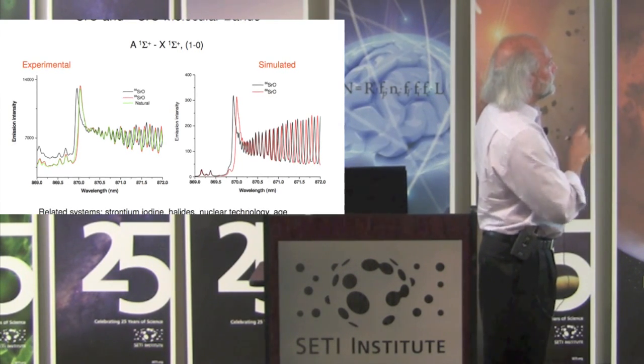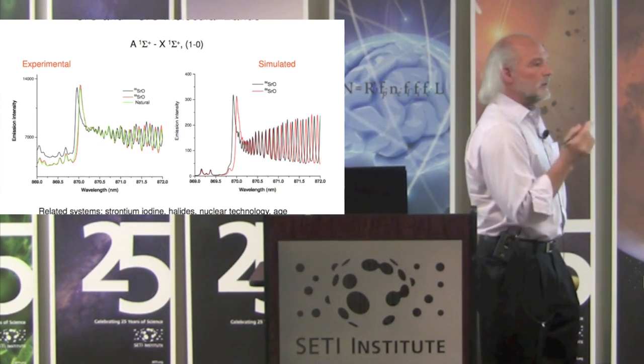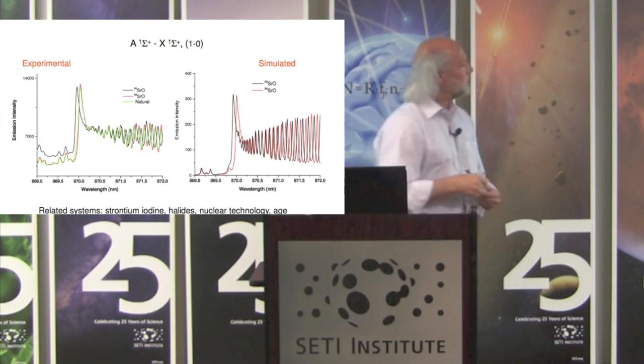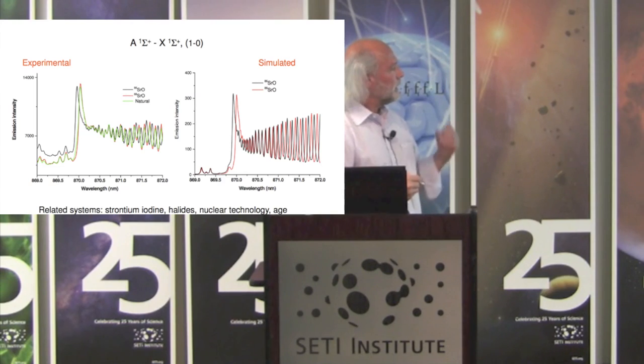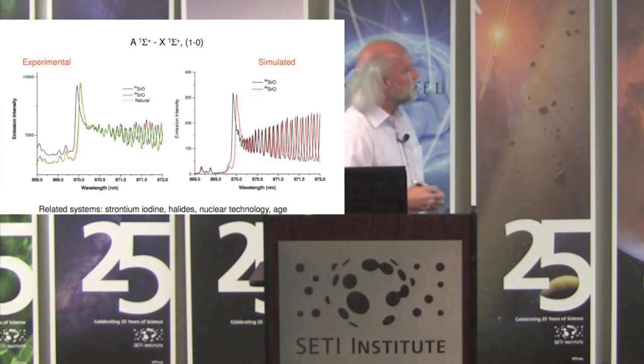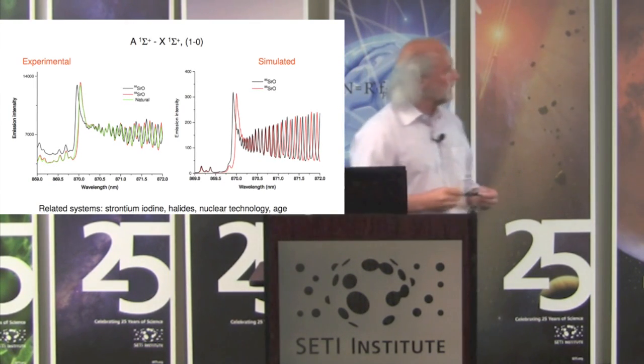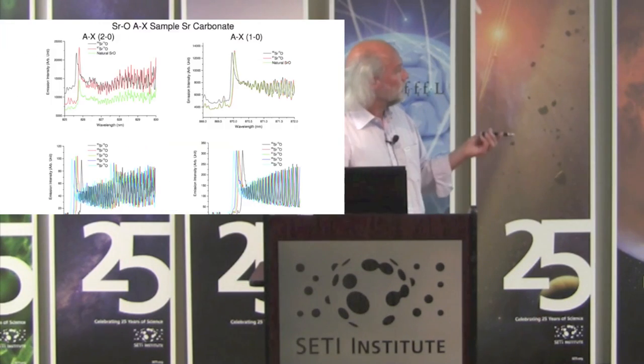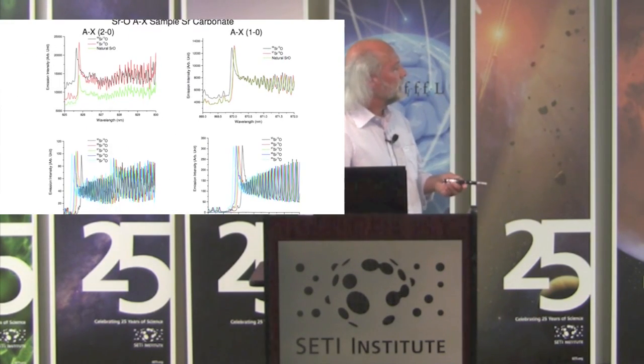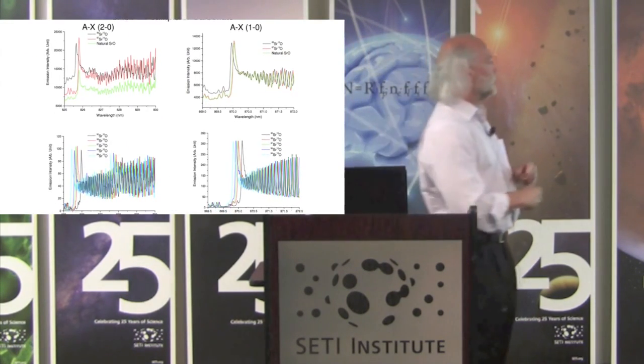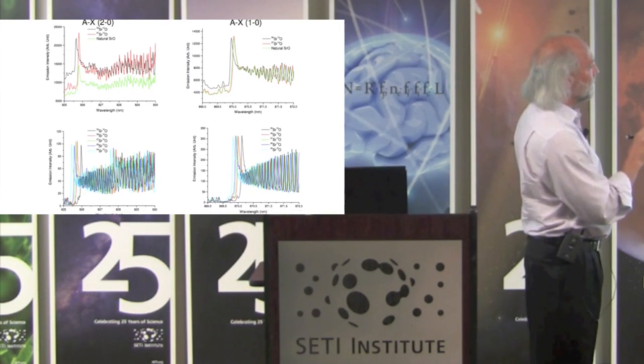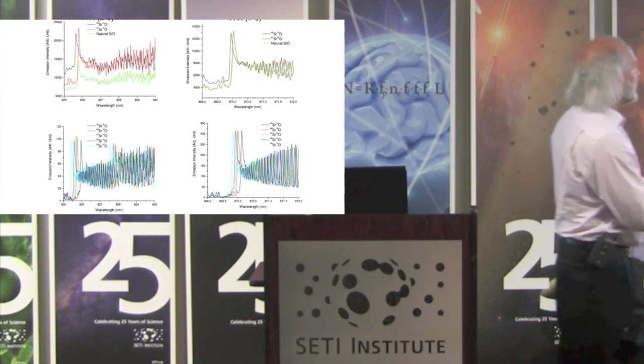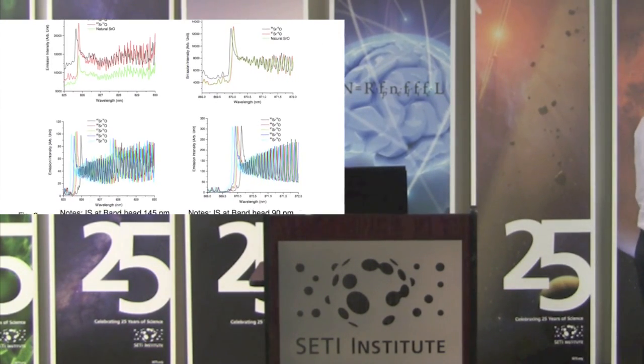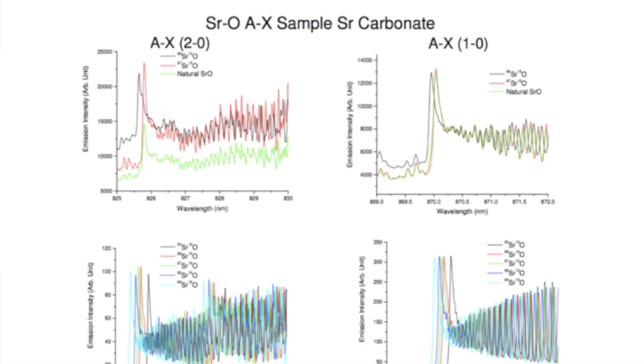So these are measured data. You can see the strontium 86, 88. No other way to do this without being in a vacuum and without doing something like a very, very high accelerator mass spec or something like that. So it's pretty cool, one laser shot. Again, we're spending a lot of time on strontium. We have models to predict what the spectra should look like. We're doing the calculations for all of the strontium isotopes, and again, you should be able to see pretty good shifts.